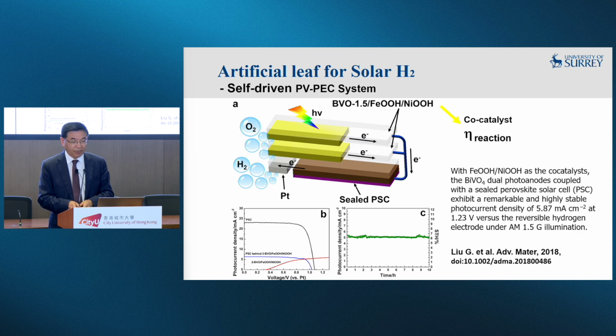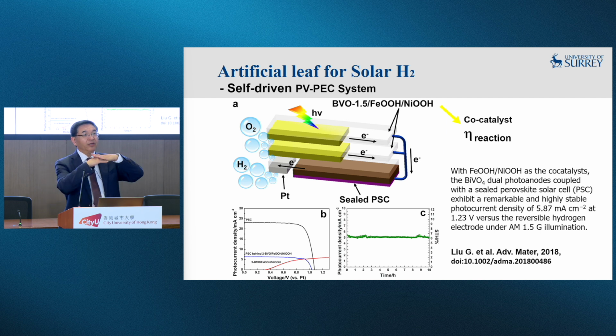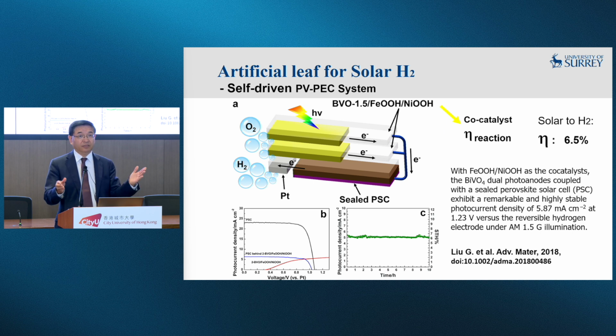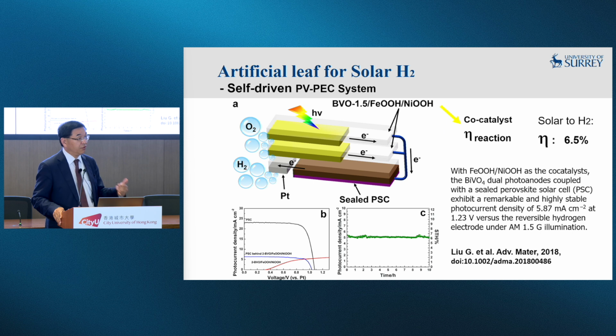So one of my former students, who is now a professor at the Chinese Academy of Sciences and director of the Institute of Metals Research in Shenyang, is very clever because he designed this tandem, a so-called artificial leaf, for solar-to-hydrogen conversion. Basically, it is a perovskite solar cell integrated together with two co-catalysts, iron and nickel oxyhydroxide, on this bismuth vanadate photoelectrode. And he produced this very high photocurrent, and the direct solar-to-hydrogen efficiency for this device is about 6.5%, right?